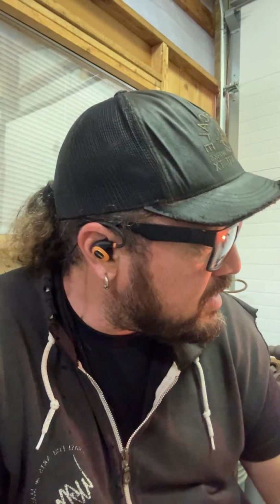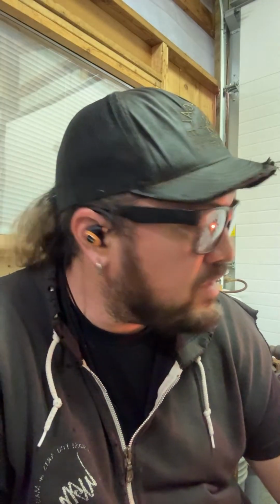The reason I want to pull the temperature down is because now I'm going to allow the steel to soak in the forge for like 20 minutes. Now, it doesn't need to be at welding temperatures. It just needs to be hot enough so that the carbon is still moving pretty readily within the material. I explained this yesterday, but I'll explain it again.